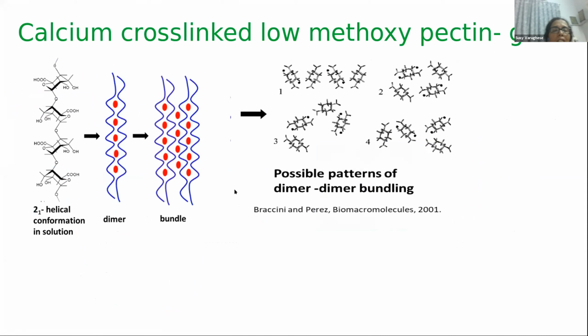So with calcium cross-linking, not only are the dimers formed, sometimes these dimers also bundle together and form stiffer parts in the network. So in the gel, when it is forming, the assumption is that they form this kind of egg box bundles or egg box dimers.